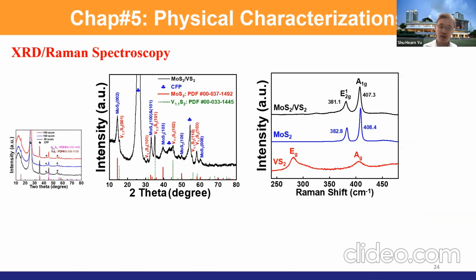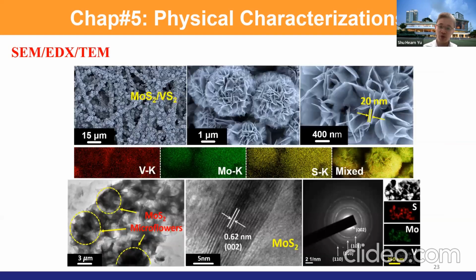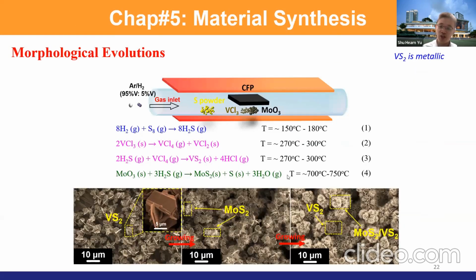Vanadium is not VS2, it's V1.1S2. The vanadium can diffuse into the MoS2 structures slowly, and then eventually it will dope the MoS2. When we look into the byproduct here, we find that some of the byproduct should not have extra vanadium source to dope into MoS2. The vanadium source should have already depleted. So we believe the doping process goes through solid diffusion from the underneath VS2 into the MoS2.